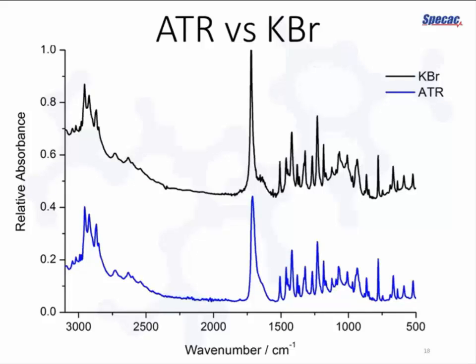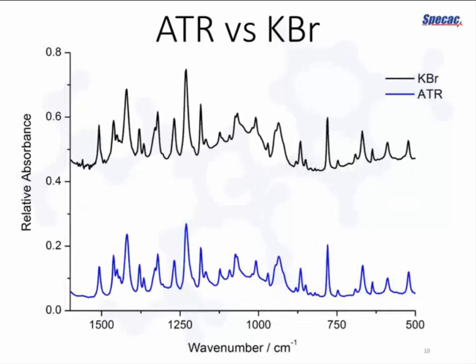And what's very clear is that the features are exactly the same, the relative intensities of the bands are the same, and there's practically no difference. If we focus in on the lower wave number side, typically called the fingerprint region, where large organic and pharmaceutical molecules are typically investigated with more scrutiny, we can see again that the absorption bands are pretty much identical. There is a subtle difference, however, in that the baseline for the spectrum recorded with the ATR is a lot more flat than that recorded with the potassium bromide.